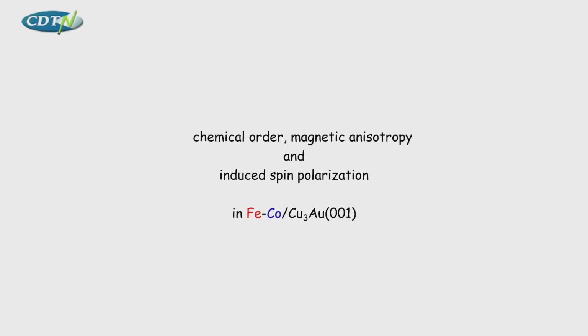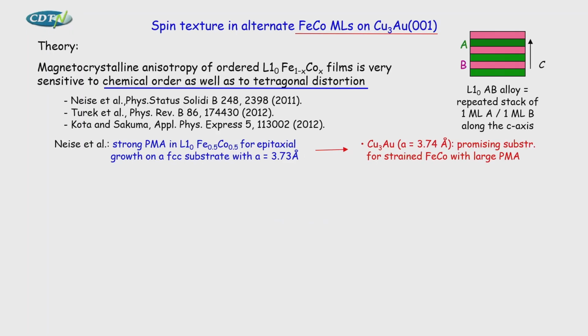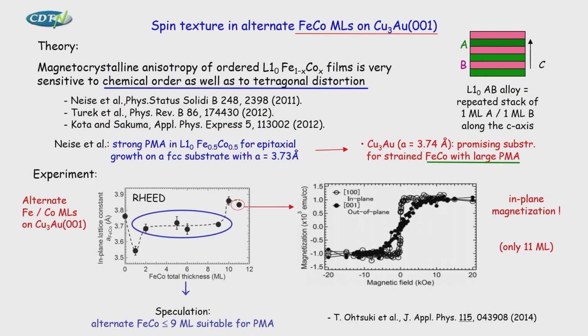Okay, but not only tetragonal distortion can contribute to the perpendicular magnetoanisotropy. There is a recent theoretical work showing that the chemical order can also contribute. It's very important for perpendicular magnetoanisotropy. And they propose that the Cu3Au lattice parameter will be very important to get this. If you get this parameter, this distortion, plus this chemical order, you could get perpendicular anisotropy in iron cobalt. And the only experimental result we had at that time was this work.